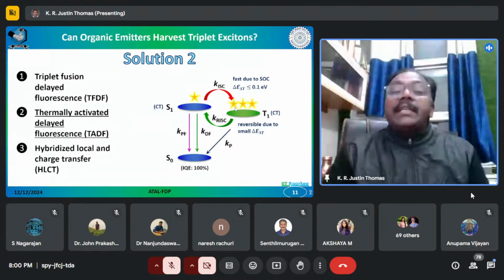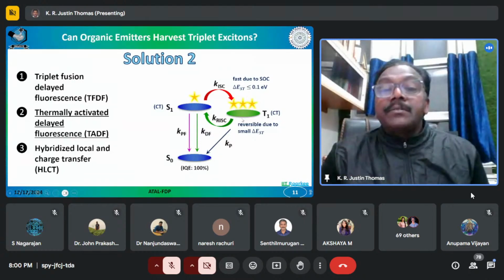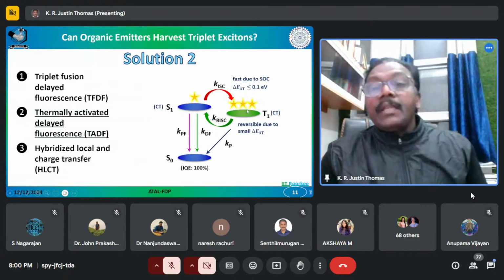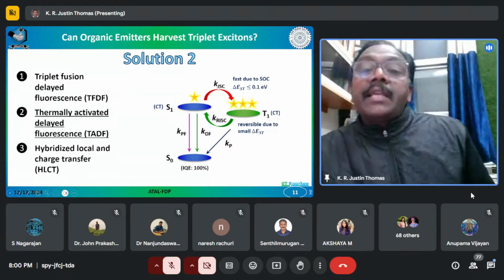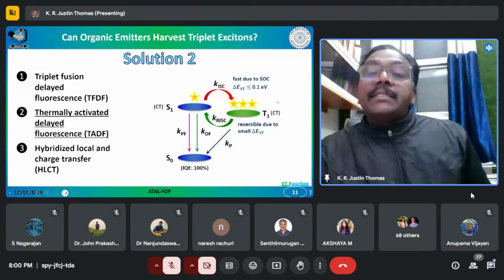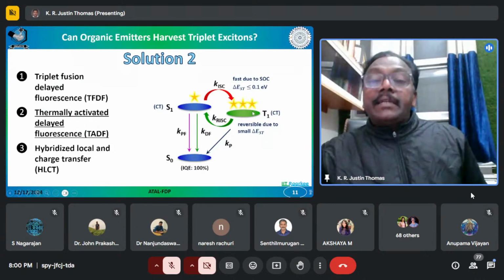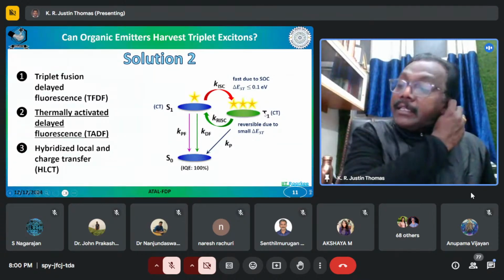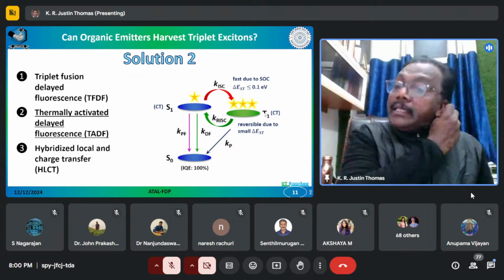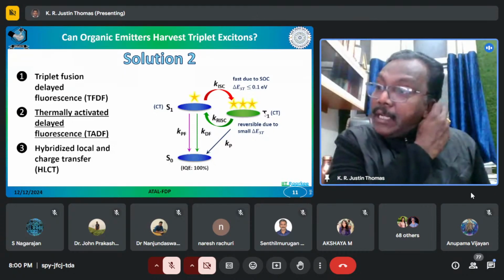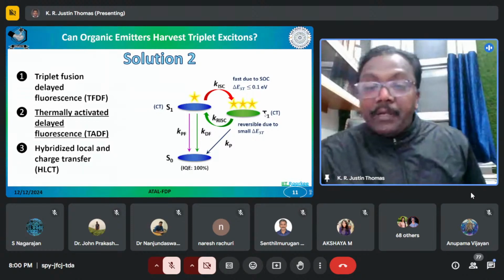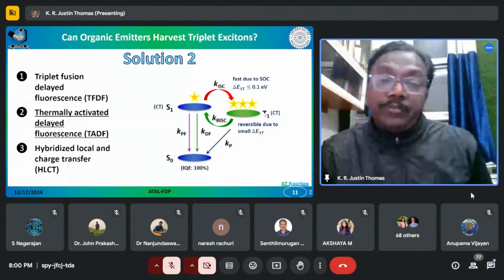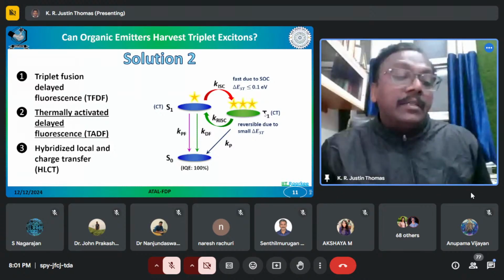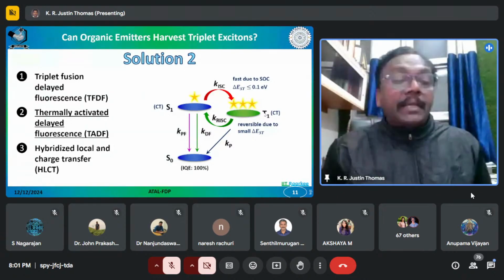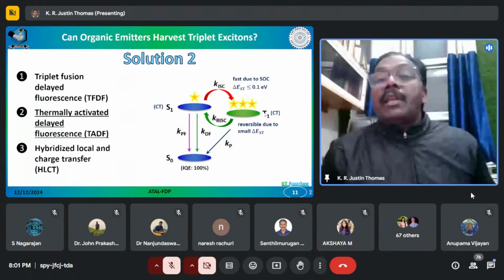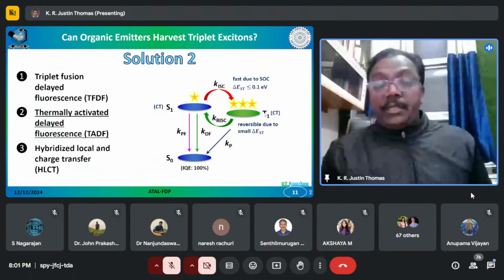And these kinds of molecules generally have charge transfer characteristics, in both singlet and triplet states. And in order for fast SOC to take place, the triplet excited state should have some LE characteristics. You might have learned that inter-system crossing can be facilitated by spin-orbit coupling, when the orbital natures are slightly different. That is what is happening in benzophenone. Because of the n to pi star transition associated with it, the n orbital and pi orbitals are different in nature, so you will have a very good SOC there.